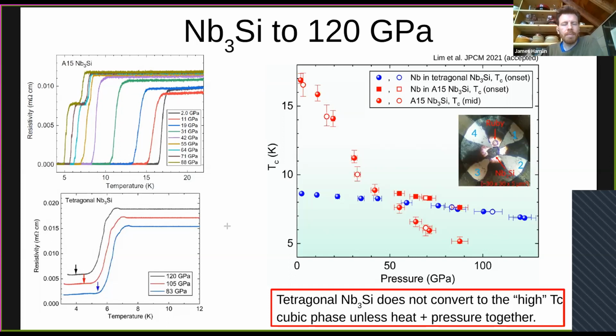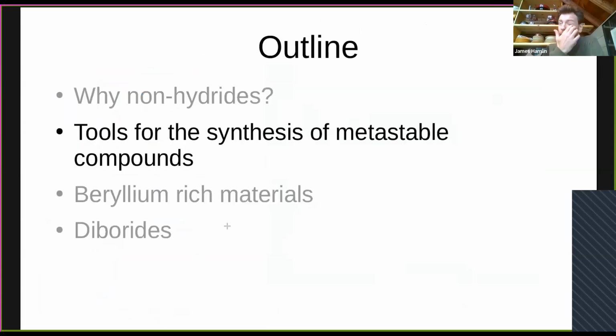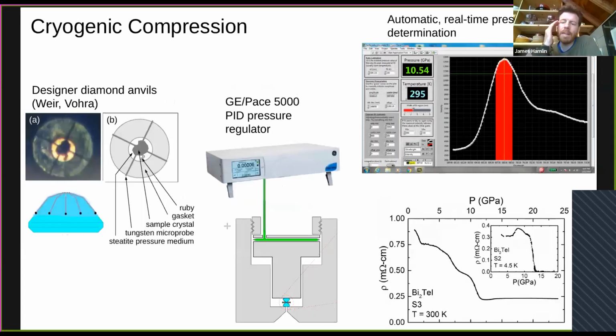Okay, so let me talk a little bit about various tools for the synthesis of metastable compounds. And there are a lot of them out there, but I'm just going to talk about a small segment of them that we're interested in. And so one thing we've been exploring is cryogenic compression. So rather than applying pressure at room temperature or even liquid nitrogen temperature, we can apply pressure all the way down to about 2 Kelvin. And we do this continuously.